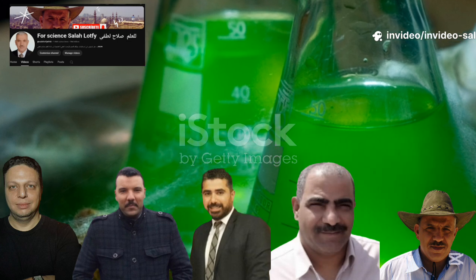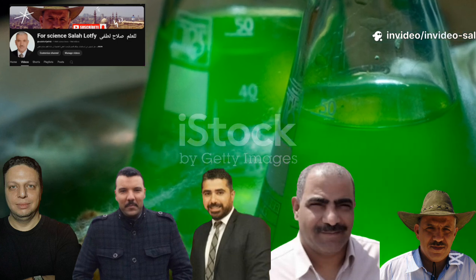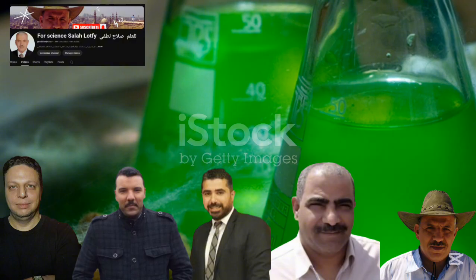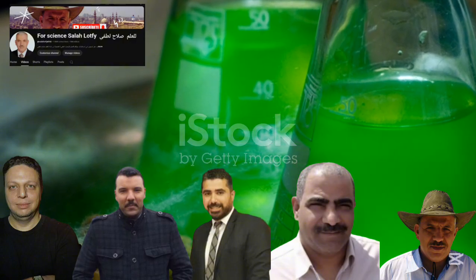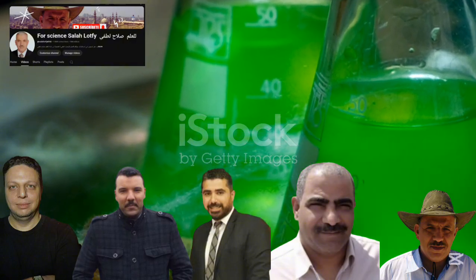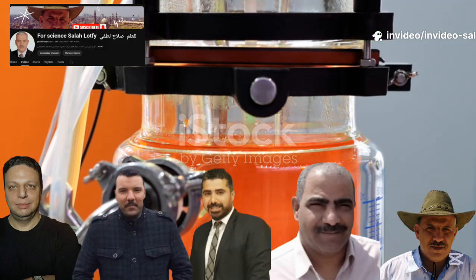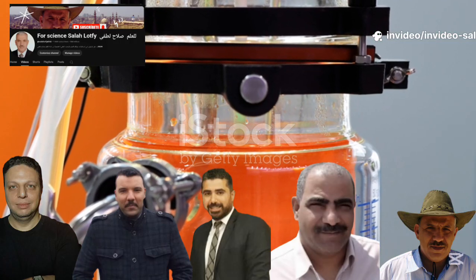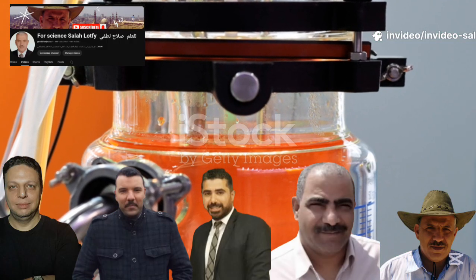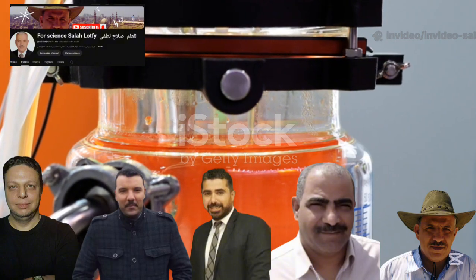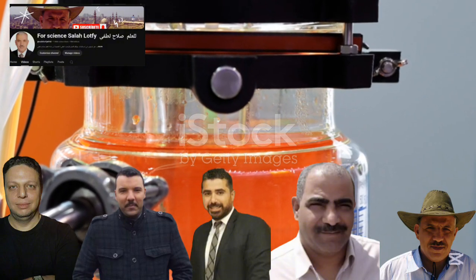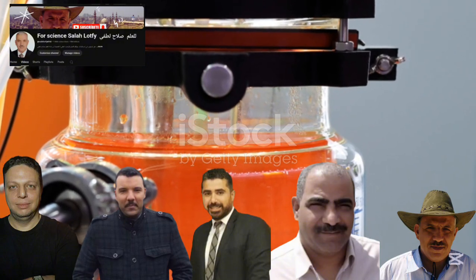The mixture is heated under reflux, a process where solvent vapors are continuously cooled and returned to the flask, allowing the reaction to proceed at a constant, elevated temperature without boiling away. After 3 hours of reflux, the reaction is complete, signaled by the formation of a deep violet precipitate. This solid is our desired Schiff base ligand. Now, we must isolate and purify it.